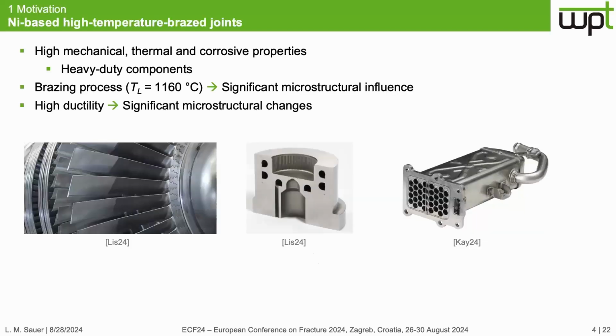To the motivation, nickel-based high-temperature brazed joints are often used for heavily loaded components because of their high mechanical, thermal, and corrosive properties. The brazing process with a temperature of about 1160 degrees has a significant influence on the microstructure, for example, a high reduction in the dislocation density. When the brazed joints are subjected to high stress after the brazing process, this has another significant influence on the microstructure, for example, an increase in the dislocation density, which then affects the fatigue behavior.